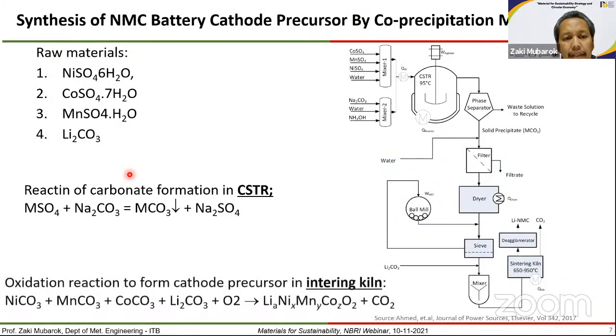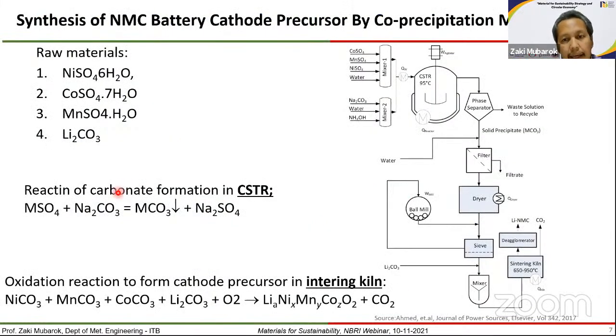And this is one of the methods which is possibly utilized for synthesis of cathode precursor material by using co-precipitation method. So the raw materials are nickel sulfate 6H2O, cobalt sulfate 7H2O, manganese sulfate, and lithium carbonate. At the beginning, the sulfate material is mixed in continuous stirred tank reactors and converted to carbonate. So the carbonate is separated, and then after size reduction and drying, it is mixed again with lithium carbonate and sintered in a sintering kiln to produce the oxide precursor material.